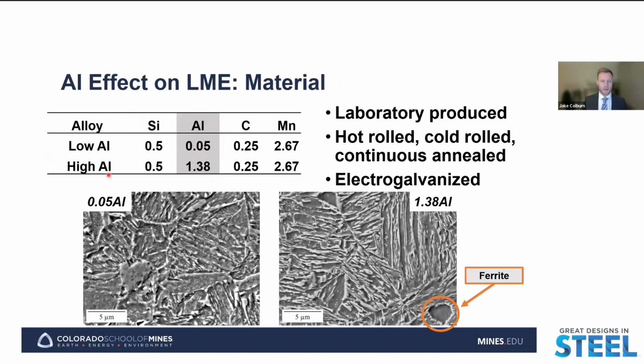So again, if we take a look at the microstructures of these two alloys, what we see is what we expect for a quench and partition microstructure: relatively high volume fractions of martensite, and some retained austenite. But then notably for our higher aluminum alloy, we see still some ferrite present. So this darker contrast region here, we would identify as ferrite, also up here in the top of the micrograph. And due to the higher AC3 temperature of the high aluminum alloy, likely full austenitization was not achieved during the continuous annealing simulation. So there's potentially some ferrite still present near the surface of this alloy.